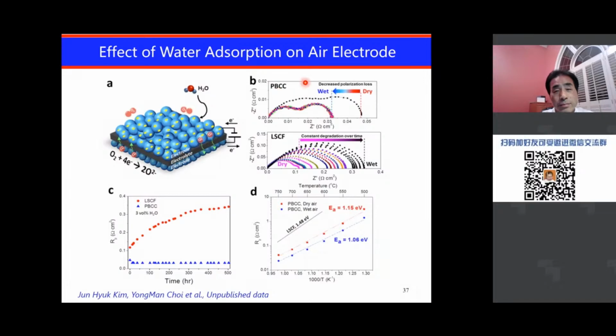In contrast, for the PBCC here, when you introduce some water into air, the impedance actually decreases. As is clearly shown here, for PBCC, first of all, the impedance is small, but it also decreases as you introduce water vapor. And so that really made us try to explain what's happening there.